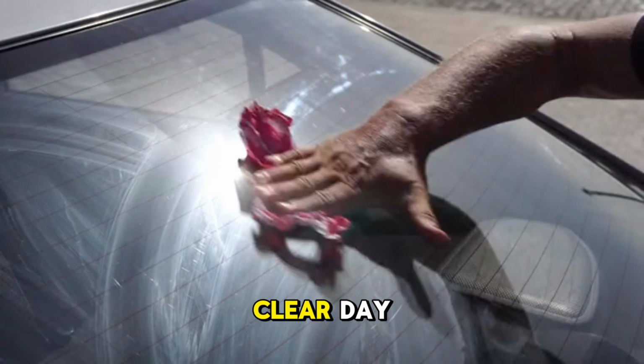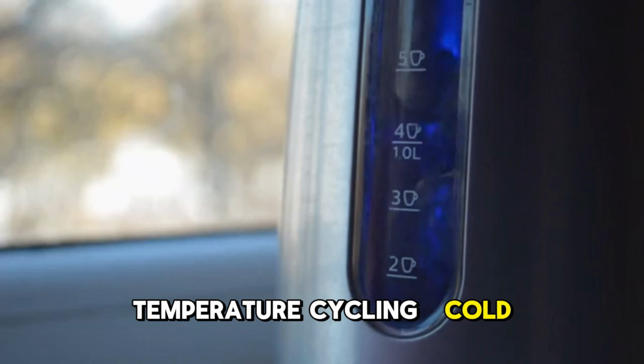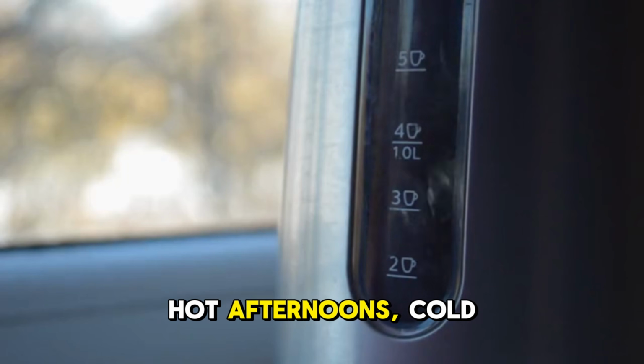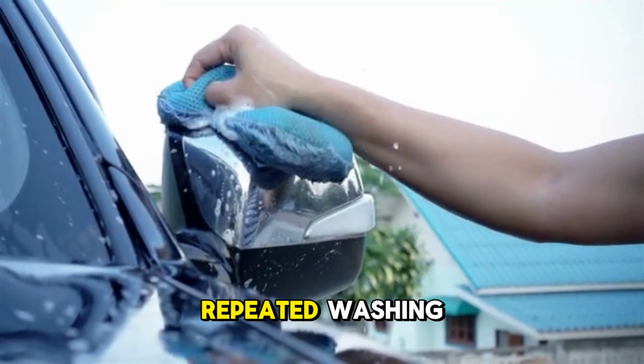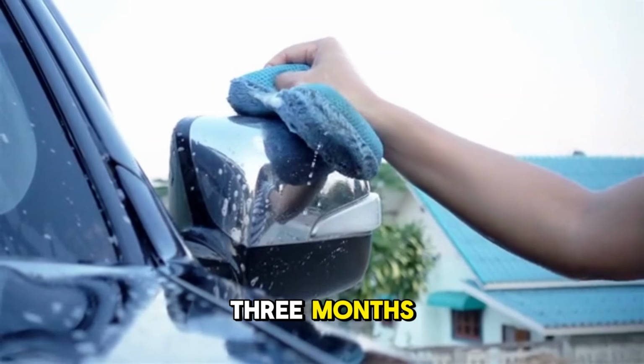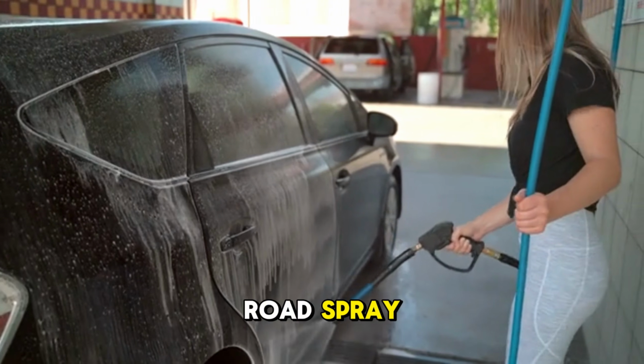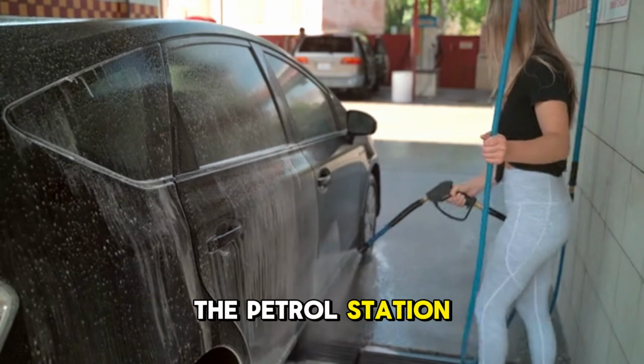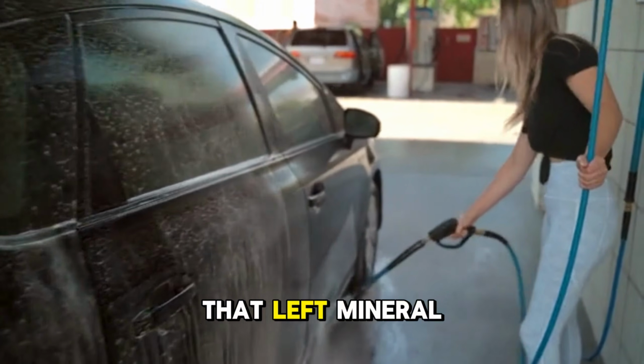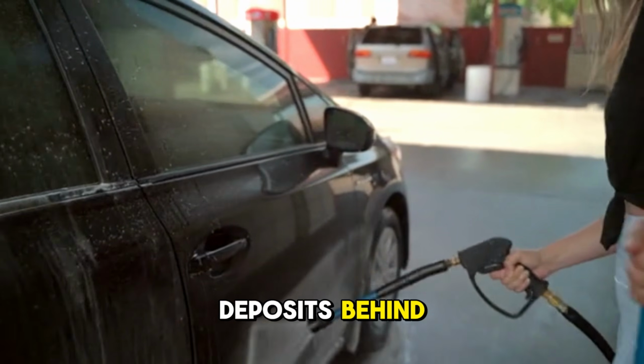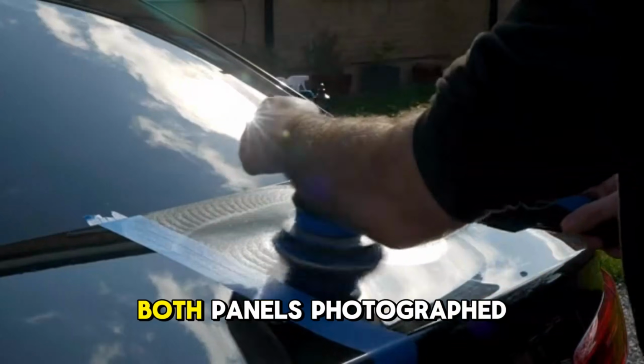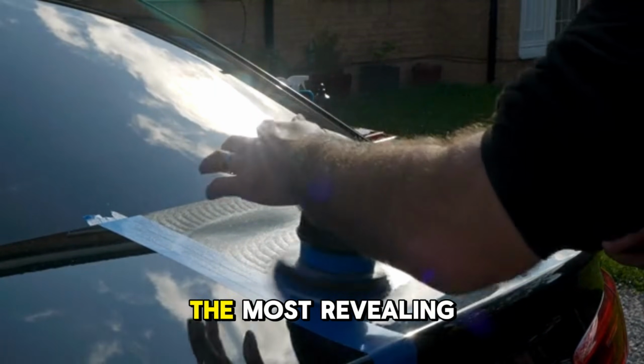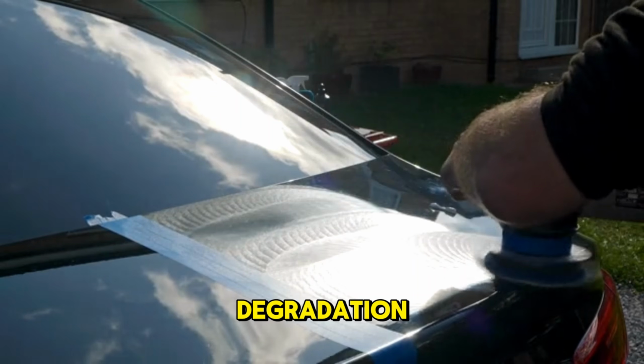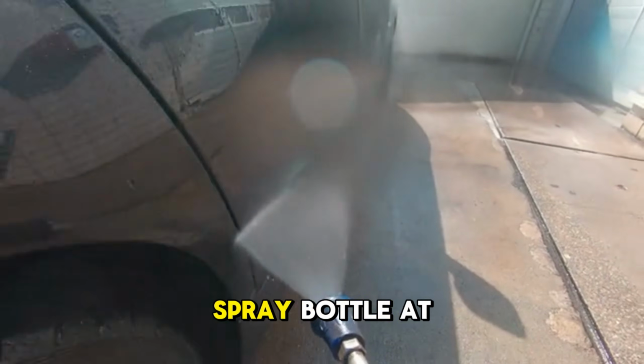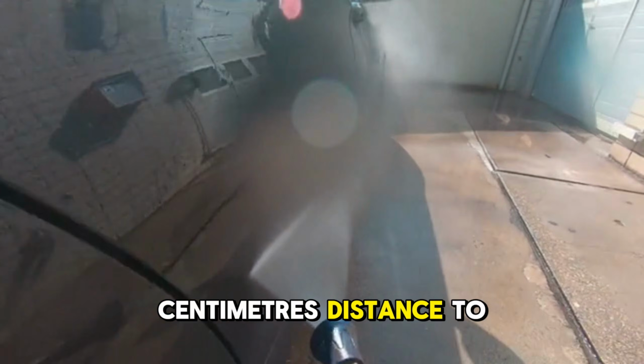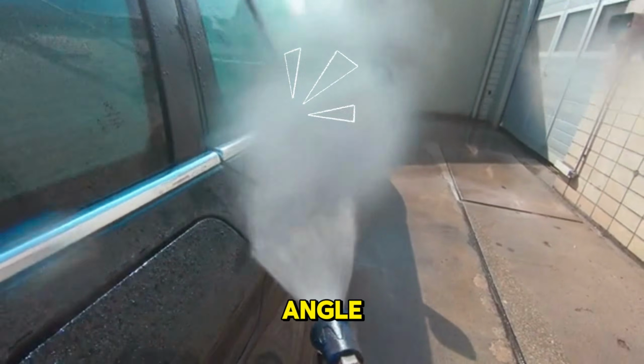UV radiation every clear day. Temperature cycling, cold mornings, hot afternoons, cold again at night. Repeated washing, 8 washes over 3 months. Chemical exposure from road spray, fuel vapor at the petrol station, and 2 separate rain events that left mineral deposits behind. Month 3 results. Both panels photographed in direct sunlight, the most revealing condition for coating degradation. I also used a water spray bottle at exactly 30 centimeters distance to document bead contact angle.